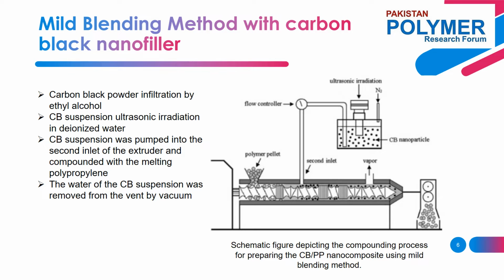Polypropylene was put into the extruder and melted at 170 degrees in the kneading block at the end of the feeding section. After that, carbon black suspension was pumped into the second inlet of the extruder and compounded with the melting polypropylene in the compounding zone. The water content of the carbon black suspension was removed from the vent by vacuum to obtain the nanocomposite. Finally, the extrudate was thermally compressed to prepare samples for complete characterization of the nanocomposite.